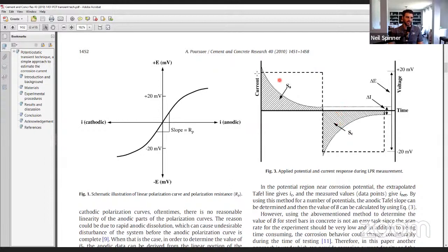What they do instead is, instead of scanning from like negative to positive or something around OCP, they pick a potential 20 millivolts or something above, they let it settle. And then they pick a potential below and they let it settle. And so what they do is then they see these areas SA and SC, they're just integrating the current. So the current versus time plot. So when you integrate that, you get charge, and they add these charges together. Okay, so this is what the transient is.